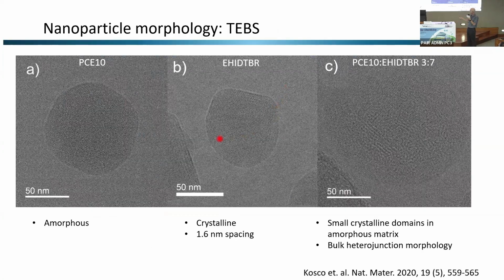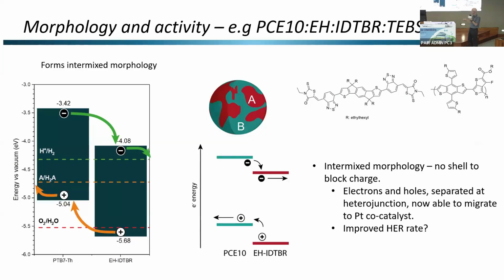You've seen the PCE10 and EHID-TBR particles before, but now we have this intermixed morphology. We've got small crystalline domains. You might be able to see a domain here. You can see another one here. There's a little bit up here and something down here. And these are randomly oriented. So this is not the same crystal. So we've got a well-dispersed, intermixed morphology. So this is very different from the previous system.